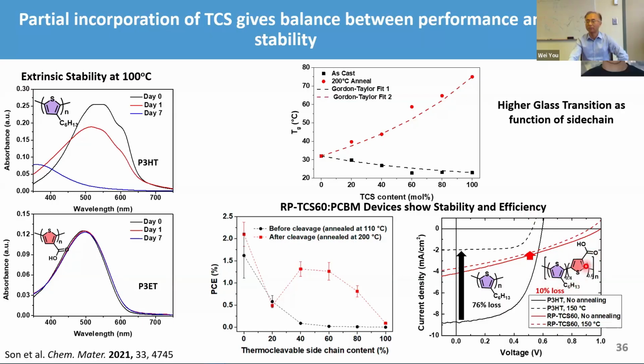But if you use the partial cleavage, you can get a high VOC, because you decorate the polymer with the carboxylic acid that reduces the HOMO level and ends up with higher VOC. But you also suffer from a smaller current, because you still lose some morphological control. But the good news is that because the polymer becomes so rigid, you only end up with a 10% loss, because the morphology is essentially locked in with this partial side chain cleavage.